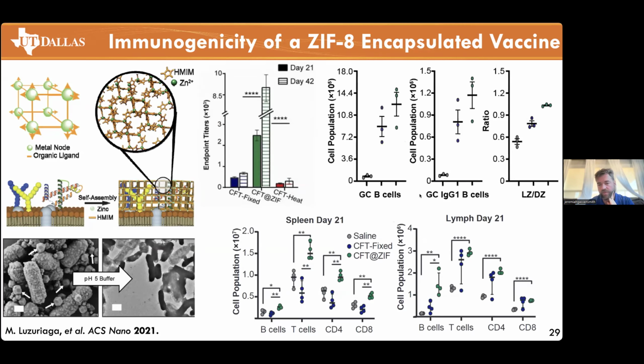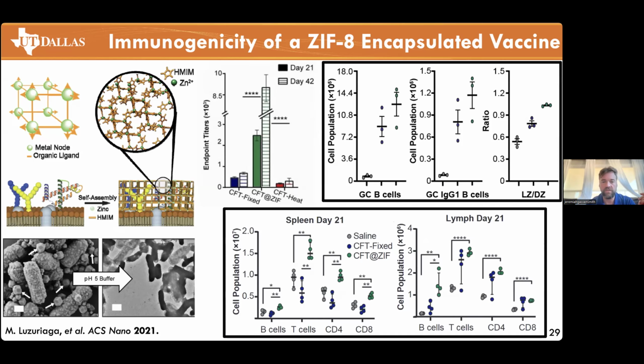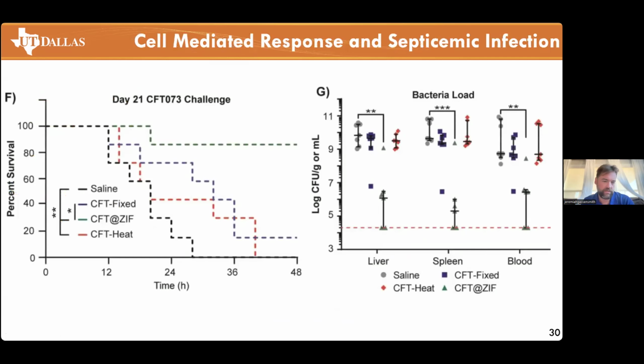And we can confirm that by looking at the germinal centers. We can look at the B cells, and we can see they're higher, and then separate subsets of B cells and the ratio of how big the germinal centers developed. All this data shows that the ZIF formulation is vastly superior to the fixed and the heat-treated formulations. And this really is borne out in the survival data.